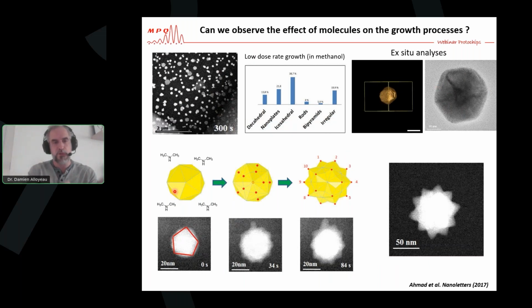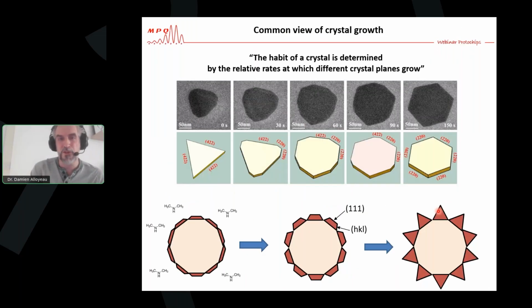And so we grow those seeds, and we use those seeds to observe the effect of the dimethylamine molecules. So during the growth, we stop the experiment, and we start injecting this dimethylamine, and we observe the effect of this molecule on the growth process. And when the molecules are in, the icosahedral nanoparticles stop growing as icosahedral, and you have a stellation process where you have arms that grow on the 20 facets of the icosahedral nanoparticles, leading to the formation of uniform nanostars. And I show this example because I want to show you that, in fact, this stellation process is not in agreement with the common view of crystal growth.